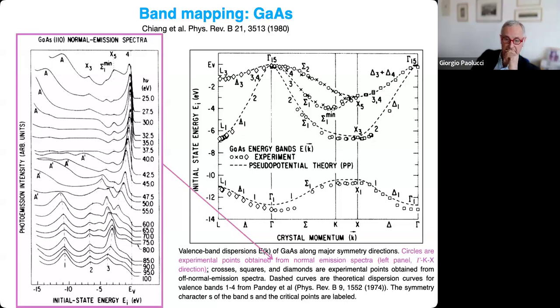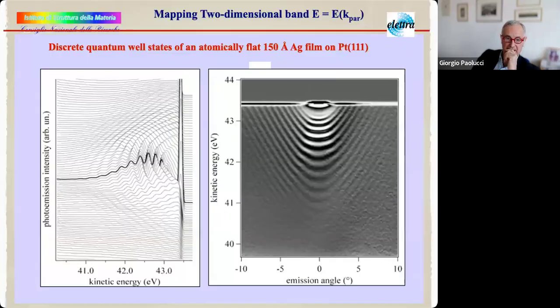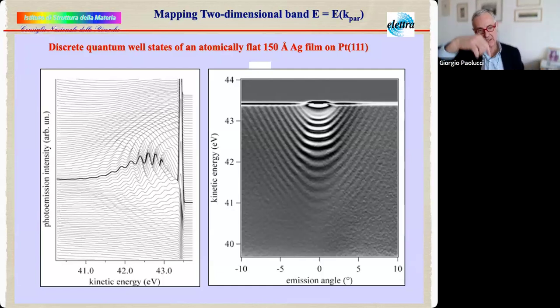Anyway, I will skip others, just to show you a nice example of a two-dimensional system. In a two-dimensional system, you map directly the band structure. So this is a silver metal adsorbed on a platinum surface, and you can see the dispersion directly. And of course, being a noble metal, you get quantization in the vertical direction, and you get free electron-like behavior in the other direction.